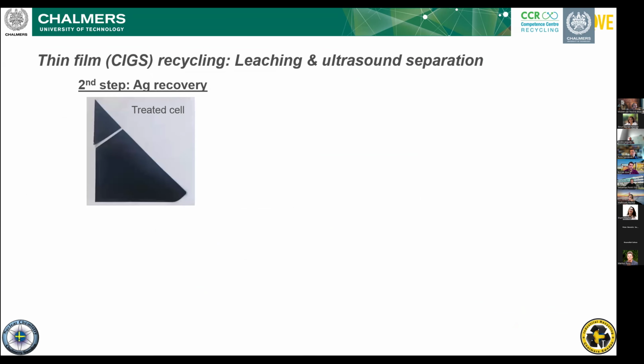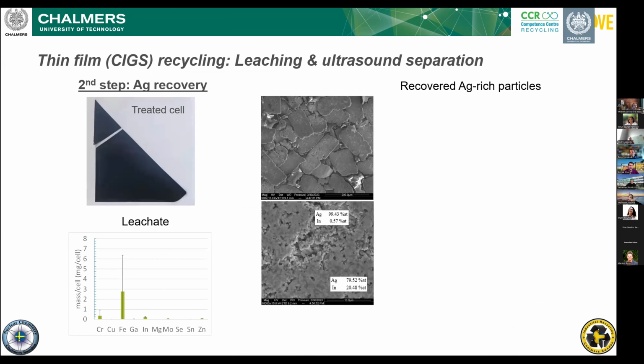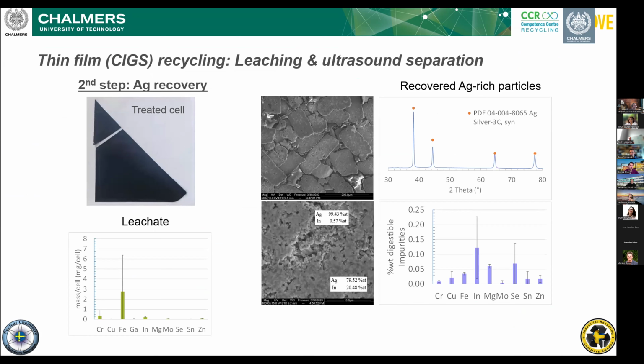In the second step, we continue with the same material, and we succeed in removing the silver by ultrasonic treatment. In this step also, we only have a really small amount of impurities of indium and some others. So the purity is almost 99% silver.